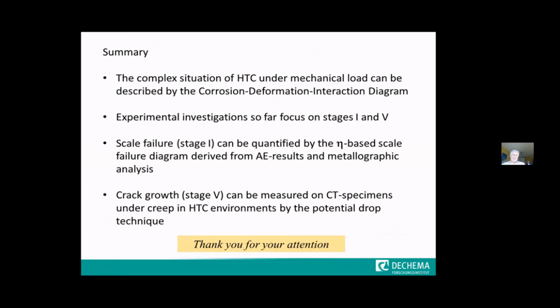So I think that takes me to the end. As a brief summary, I showed you that the complex situation of high temperature corrosion under mechanical load can be described by such corrosion deformation interaction diagrams. What I showed today, and this is also pretty much what you can probably find in the literature, is that the experimental investigations that have been done so far very much focus on the first and on the last stage in materials life under such conditions. We've seen that the scale failure in stage 1 can be quantified by this eta-based scale failure diagram approach. What we need is metallographic cross sections for the defect sizes and acoustic emission results for the critical strains.